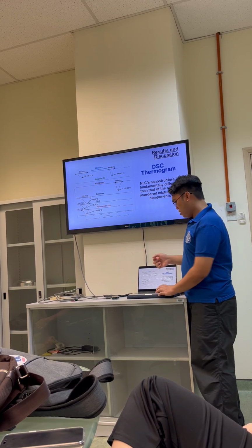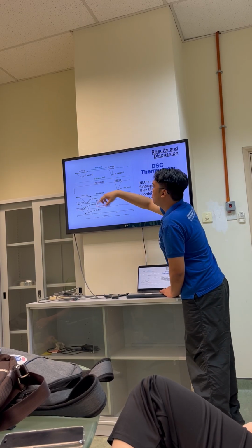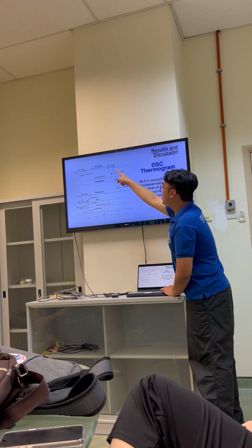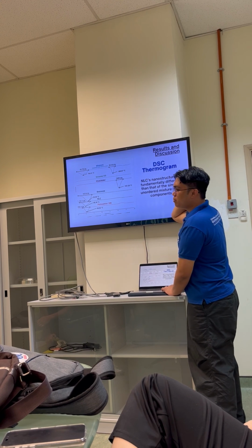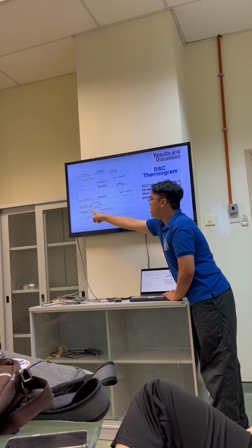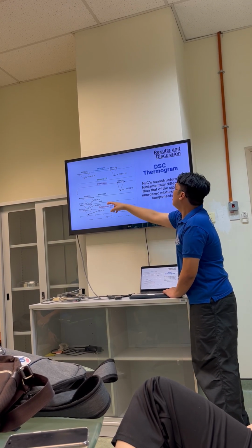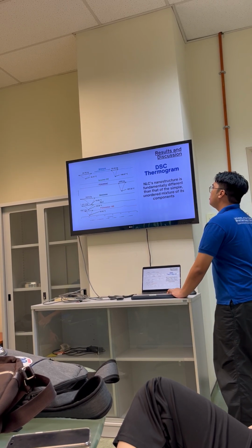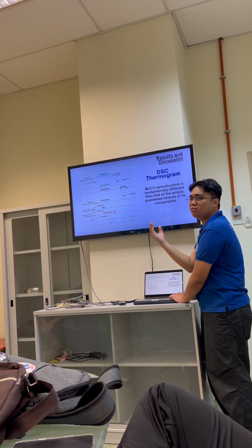So we can see here that the simple mixture alone, without any fancy emulsification method, will just attain the thermogram peaks or the thermogram recessions of the other components. Meanwhile, the NLC has its own recession or dip here, which is conclusive that the NLC's nanostructure is fundamentally different to the sum of its mixture alone.